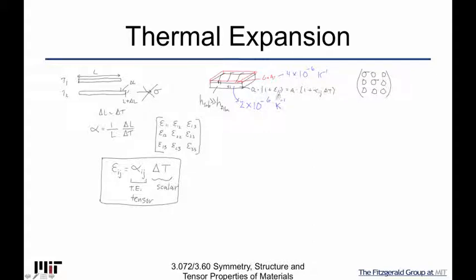And so the classic problem here is that the strain that builds up along those directions is related to the delta alpha delta T, right? So it's the difference between these two. Remember, because they're linked at the growth temperature, and as you cool, it's the difference between those two as you cool that induces the strain and the stress. And so that's just a little example of that.